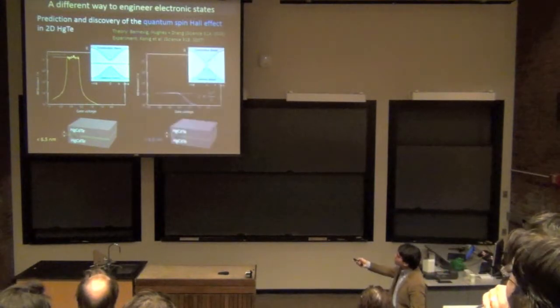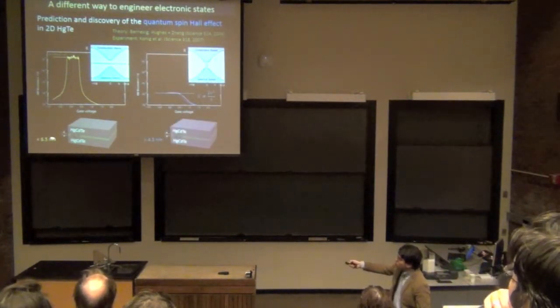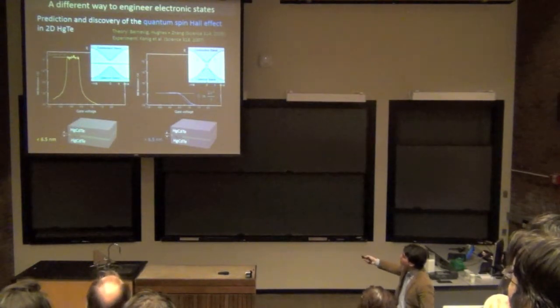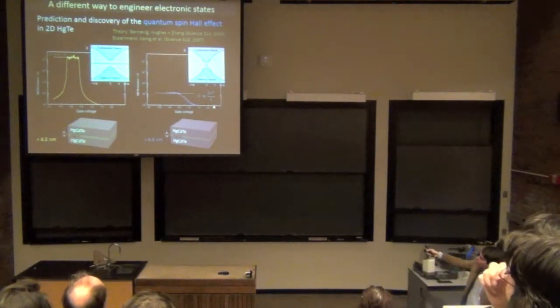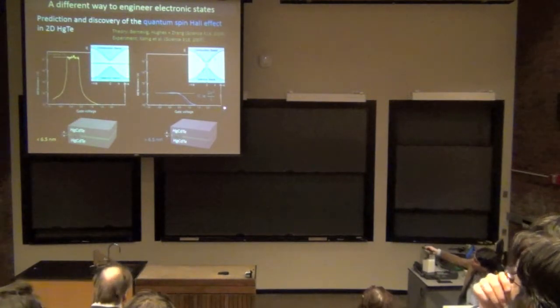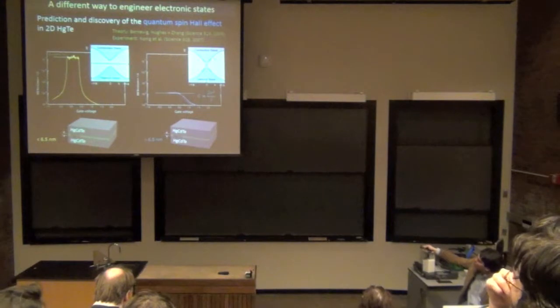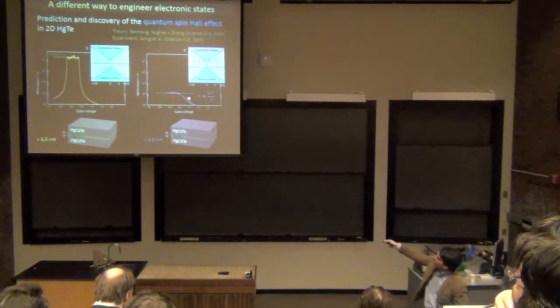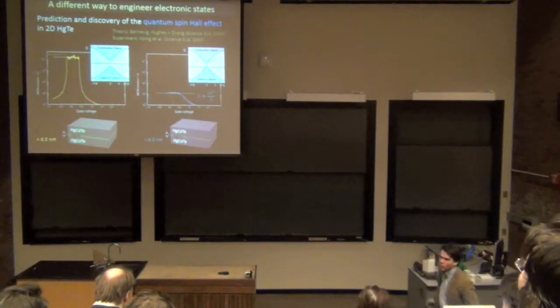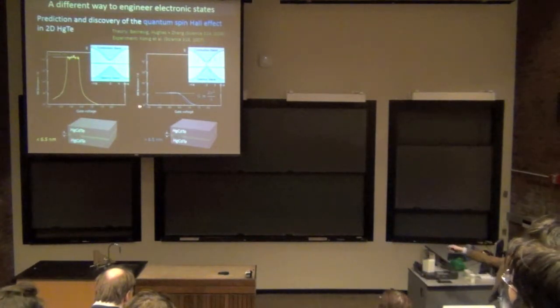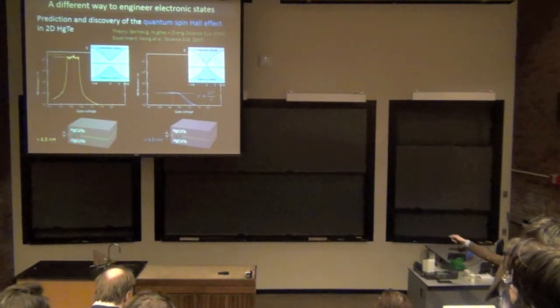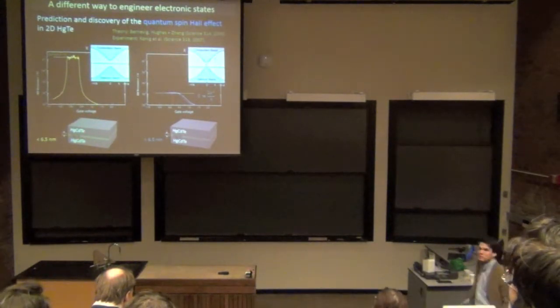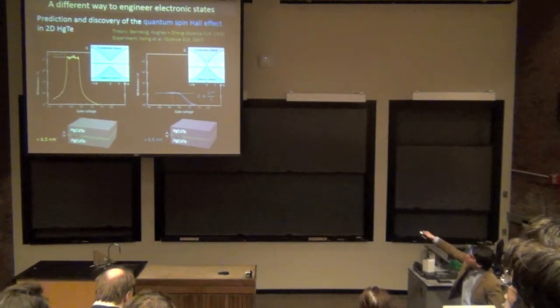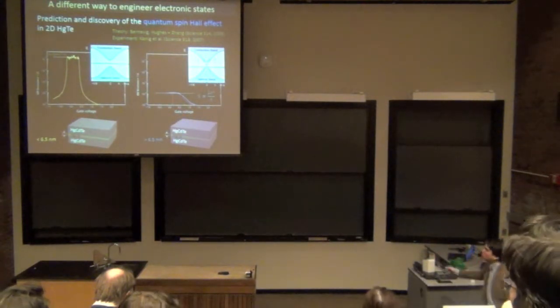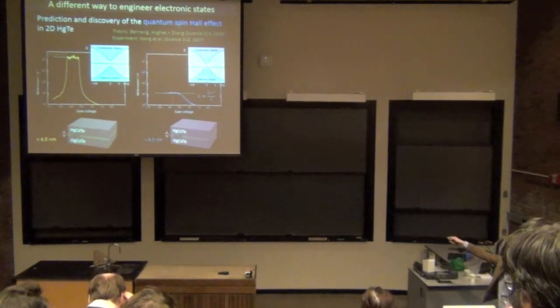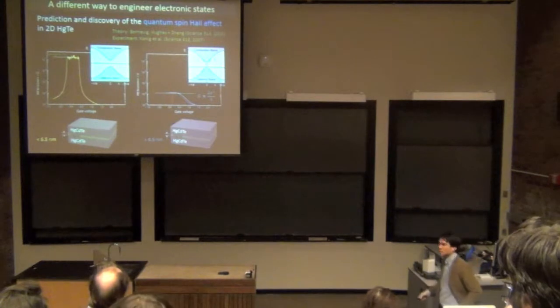The really interesting thing is when you take this structure and make it slightly larger. You can see this is really not that much larger than this, but now when you tune with the gate voltage through this bulk gap, what you see is not a really high resistance, but an exact conductance of 2e squared over h. The difference between this structure and this structure is that you have created new types of edge states, which travel in opposite directions and have a special spin polarization. So when you put the Fermi level in the bulk gap, you're just seeing the conduction of these really interesting edge states.